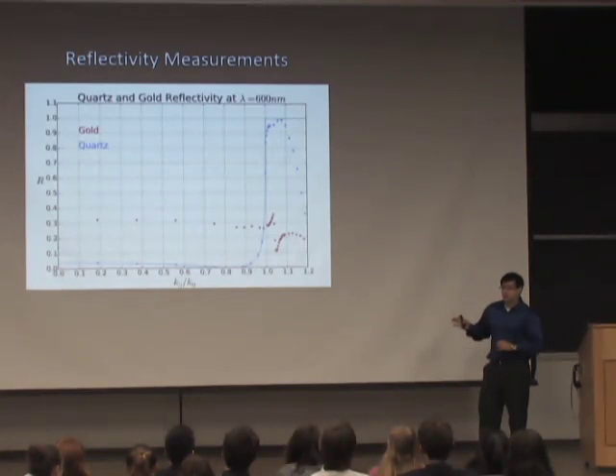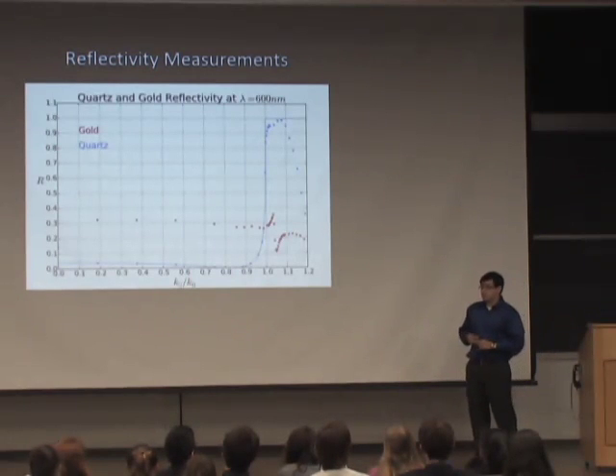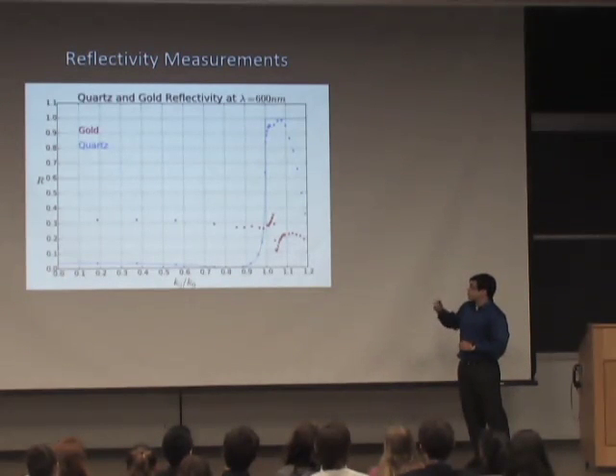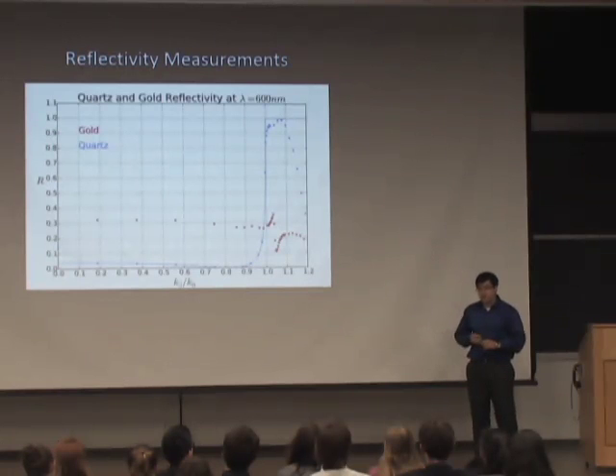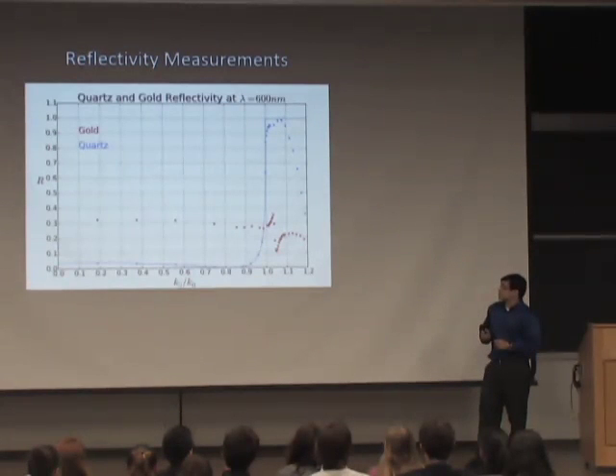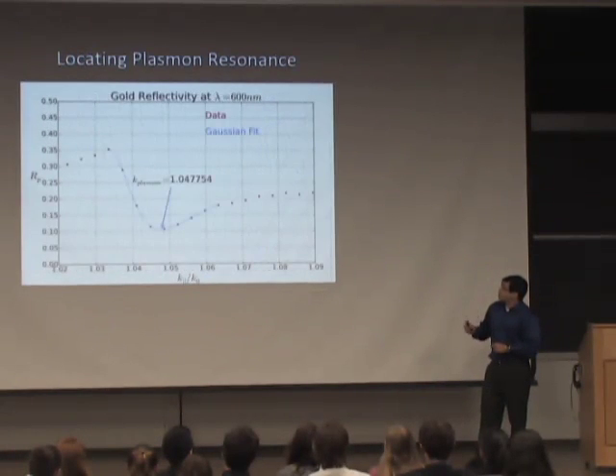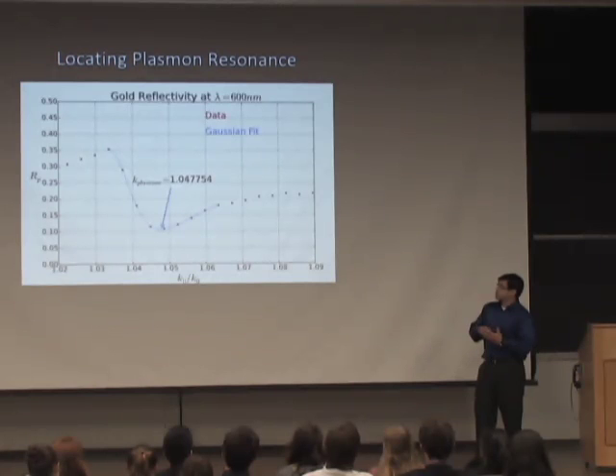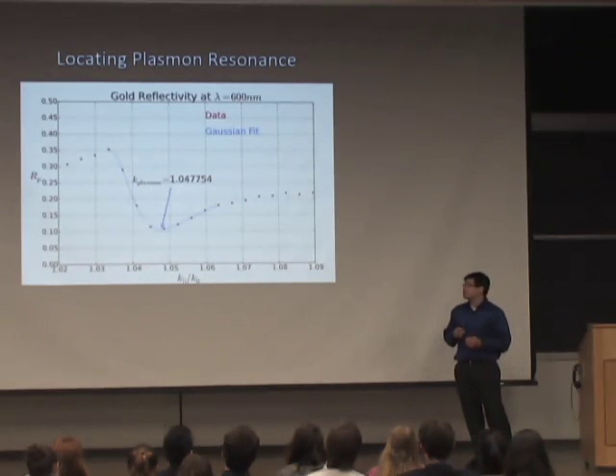And looking at the red dots is our gold data. You can see that it matches the shape of the model pretty well. There's an uptick near the critical angle, and then a drop at the plasmon resonance. So we're interested in this gold film, and looking closer at our gold data, we see a pretty good shape. And then what we need to do is look very precisely at where this plasmon resonance is.